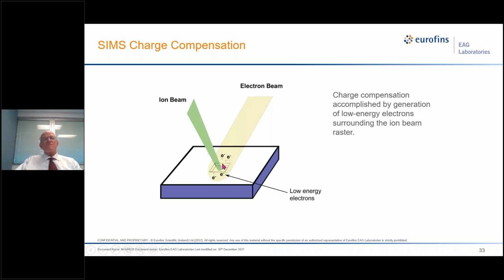Sounds easy enough. But oftentimes we're looking at low K dielectrics or SiO2 layers that are not thermal, they're deposited. And the electron beam, if you're not careful, can actually damage the insulating layer that you're trying to analyze. So you have to be very careful with the electron beam parameters to not cook the layer of interest. Low K dielectrics are famous for this, very difficult.